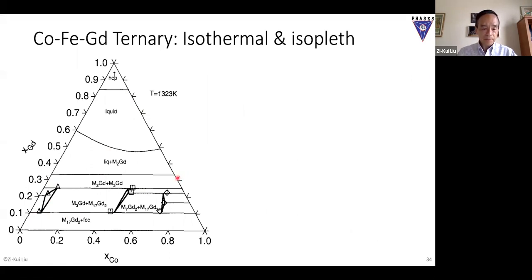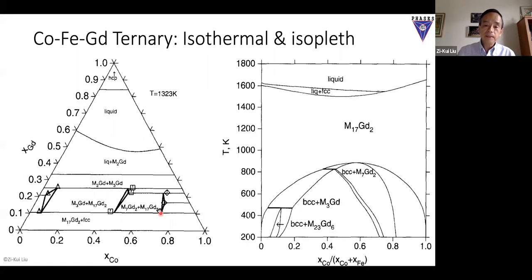Gadolinium. And then you can do the isopleth. Isopleth means a fixed composition, and you plot temperature as a function of one component. So what we're going to show is I'm going to plot this line for this compound, 17.2, exactly on this line. However, exactly on this line actually completes either side numerically, so if you go either side, it'll be a bit different. So this shows that. So this is along that 17.2 compound line here.